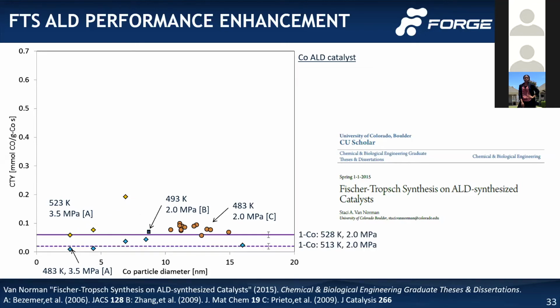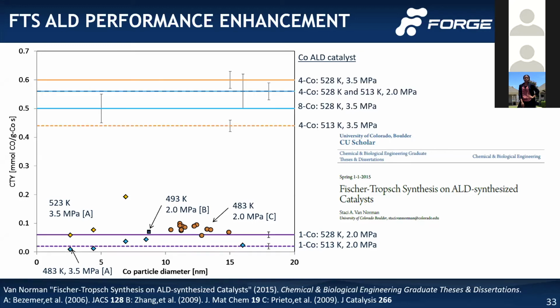In comparison, with ALD and increasing the number of cycles of cobalt deposited in a metallic method using cobaltocene and hydrogen, with one cycle you're within the same turnovers or yields per cobalt as a normal Fischer-Tropsch synthesis catalyst. But if you increase the number of cycles to 4 and 8, we're much higher than anything ever reported before. In fact, it's 3 times higher than the highest efficiency at a similar conversion of carbon monoxide and selectivity. That's important, to select points with similar conversion and selectivity so we're not comparing erroneous points.